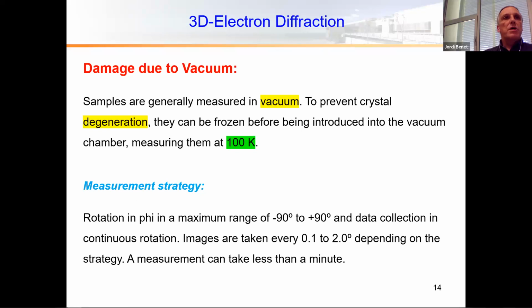And then we can measure in a strategy where we make a rotation in phi in a range. This is a bit exaggerated, let's say from -60 to +60, or -70 to +70, and make a collection in continuous rotation. We can take images in steps from 0.1 to 2 degrees. And this in total can take less than a minute if we have some diffraction in the crystal. So although the crystals are quickly destroyed, we can also measure very, very quickly so that we are always able to get some data from the crystals before they are destroyed.